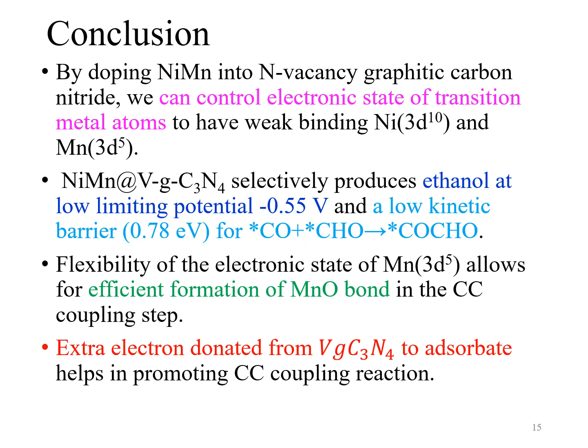As conclusion, by doping nickel manganese into this N-vacancy graphitic carbon nitride, we can control the electronic state, and this control of electronic state helps produce ethanol at a low limiting potential with low kinetic barrier.